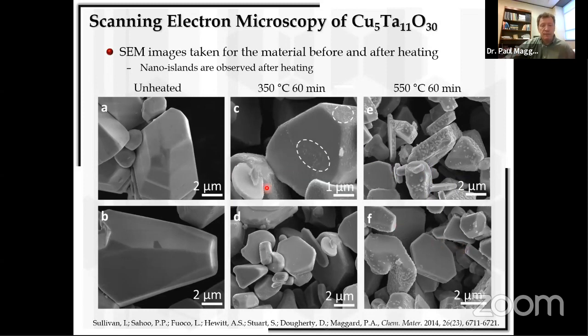So here are SEM images of, in this case, a 51130 composition, where we've made it by flux synthesis. The flux synthesis gives you nice, highly faceted crystals. And so you can see there's nothing on the surfaces. But when you heat them in air at 350, you very easily notice these little islands building up on the surface, both on the outer edges of these hexagonal platelets, as well as on any step edges formed during crystal growth, the little particles that are forming.